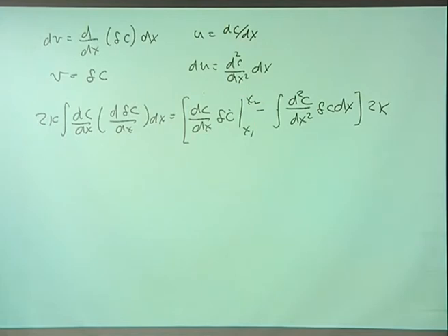So if you're doing things like spinodal decomposition in finite domains, or anything associated with the surface, these terms are very important. And I don't know how many papers I've reviewed where people forget about these terms and then use standard flux conditions, for example, at boundaries.